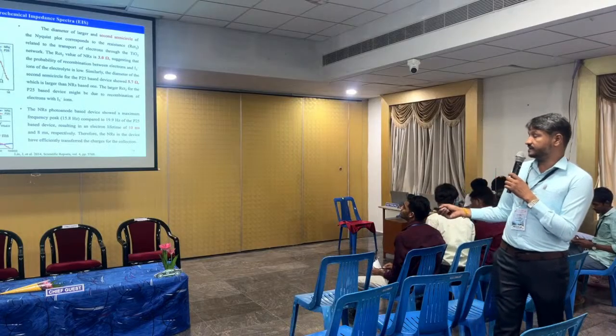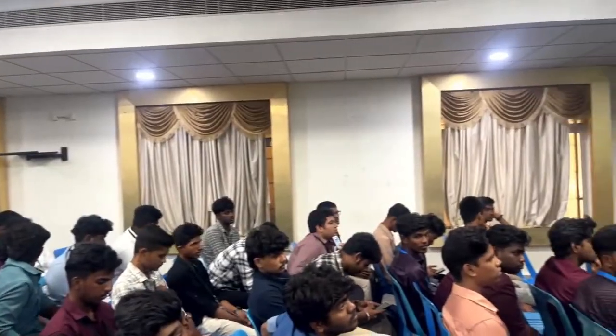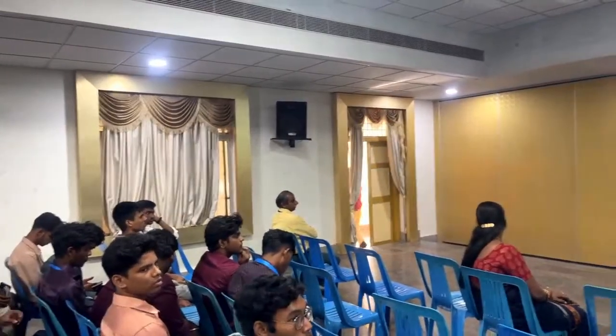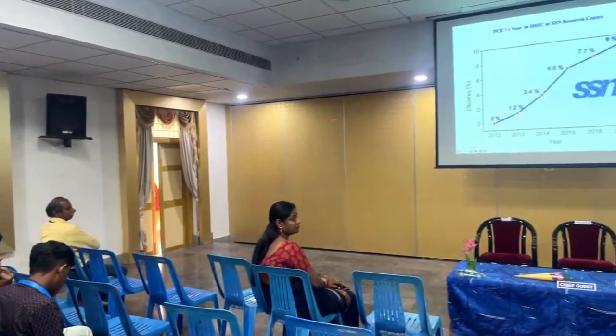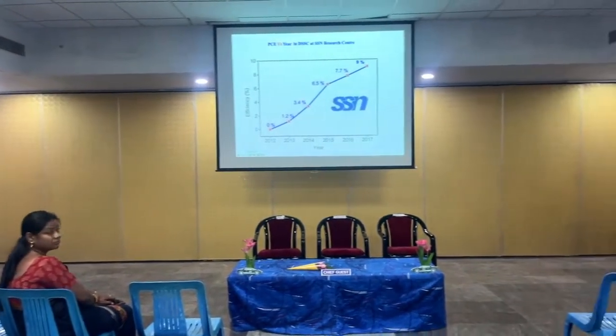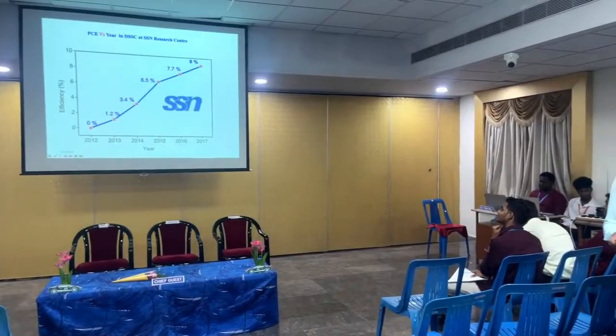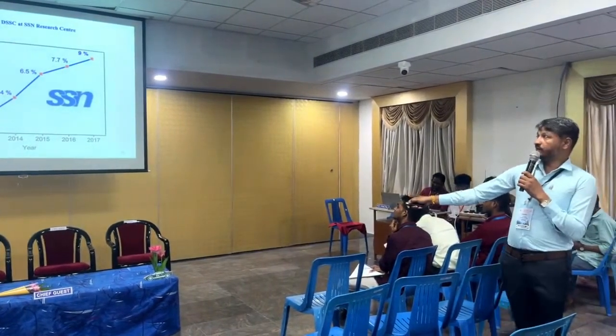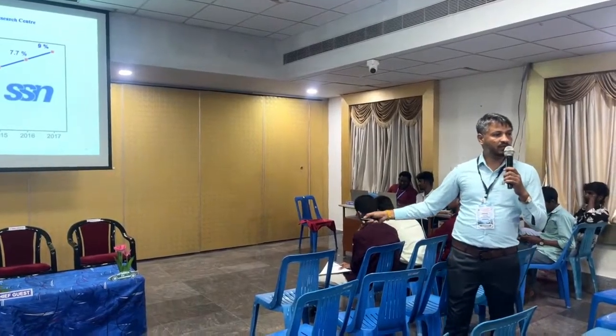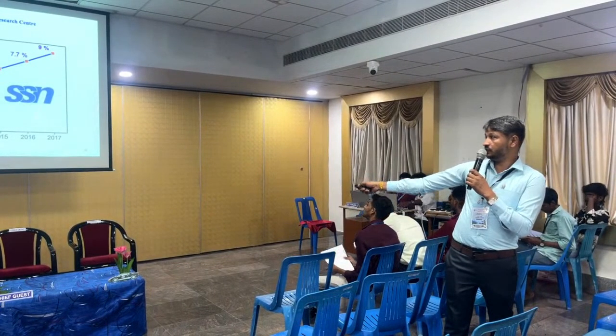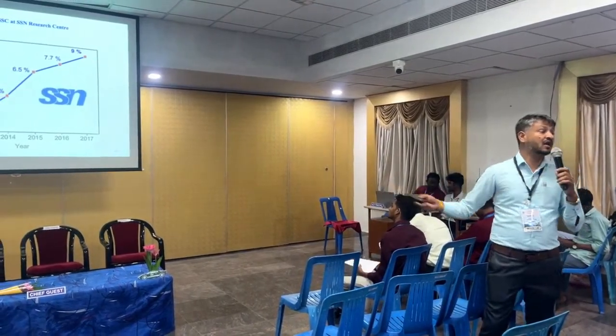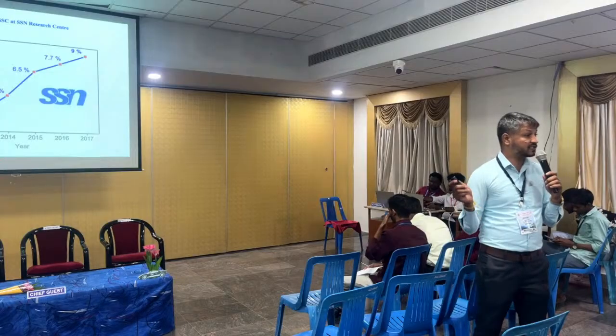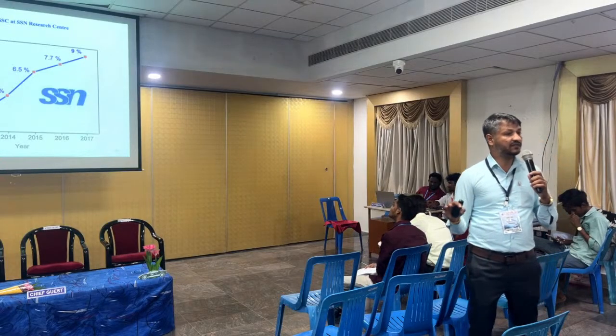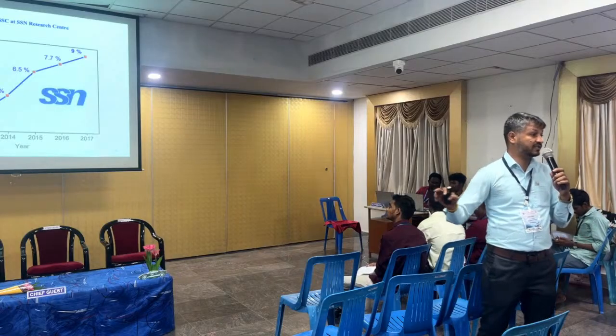And we performed the stability analysis for our fabricated device. From the solar cell, we obtained 9% efficiency with the combination of rods and particles. So we started the game in 2012 with 0% efficiency and 0% knowledge also. After a period of silence, we used different approaches to get 9% efficiency. We took this much time to get this much efficiency, which means a lot of effort is needed. The best record efficiency is 13%. We reached close to 9% in DSSC.